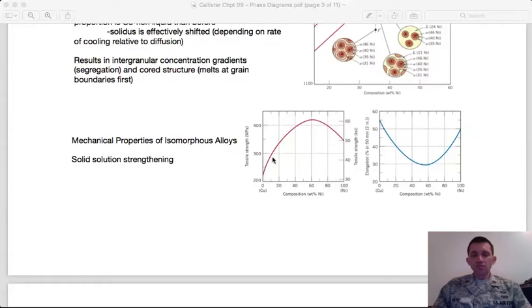And that reduces the energy of both, which means that if I'm going to move that dislocation, which is what I mean by yielding, then I'm going to need to overcome that energy gain that I had, right? I'm sitting in an energy well, essentially, and so I'm going to have to put in energy to get out of that well and move that dislocation. And so as I add more nickel, I have more of that copper lattice distortion, more of that impediment to dislocation motion, and my tensile strength increases, right?